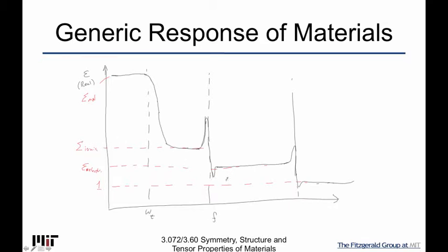So you can see here, if I'm playing with the ionic one, I can do measurements where I'm here. I can do measurements where I'm here. I can do measurements right here. This gives me epsilon real electronic, and this gives me the ionic plus the electronic, which you can't see anymore. But the point is, this gives me both, and then I can know how much the ionic component is.